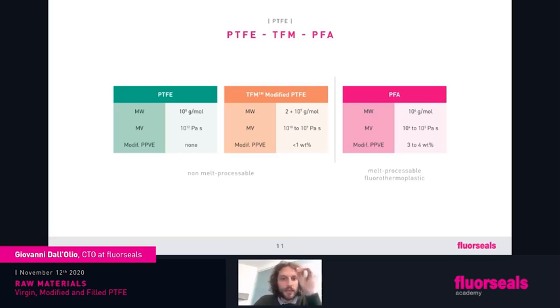Basically, we have mentioned in the last webinar that PTFE has a unique manufacturing process because even if it's a thermoplastic material, it cannot be processed by melt techniques like screw extruding or injection molding, but we do have to use our own techniques. Why? Because once you melt the PTFE, the viscosity is so high thanks to the molecular weight. We can see here the MW states molecular weight is so high that when you get to the fused material, the viscosity, so the tendency to flow of the material, is so high that it doesn't flow.